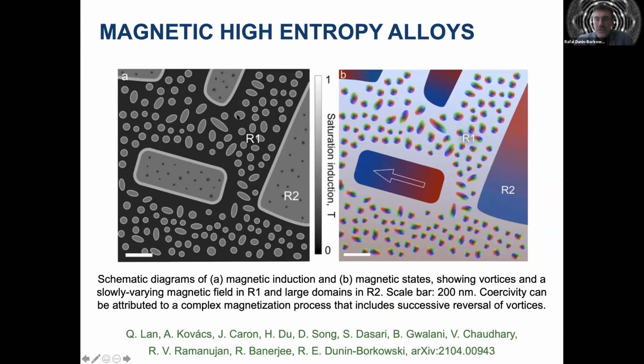And so what off-axis holography tells us for this material is shown schematically on this slide. On the left, we have color-coded in different shades of gray, regions which have different saturation magnetic inductions, which are ferromagnetic to different extents. So there are at least 3, perhaps 4 regions which have different magnetizations inside the material. They are subdivided into precipitates of different size.